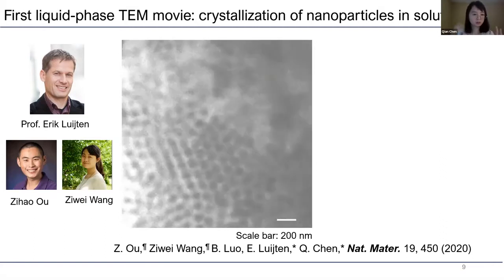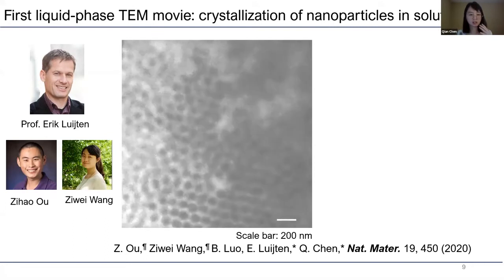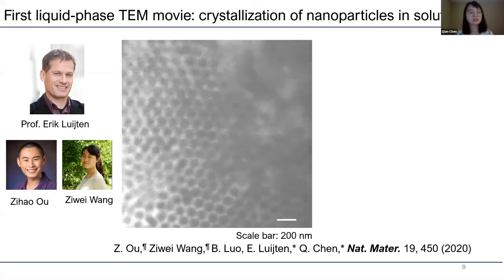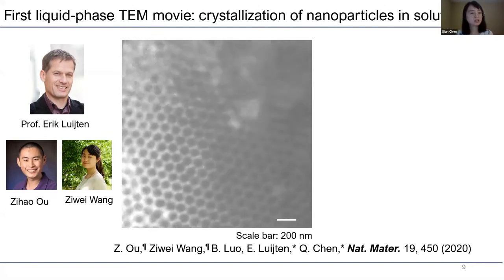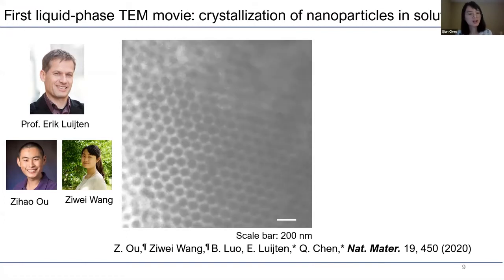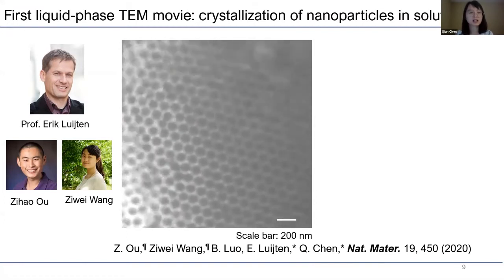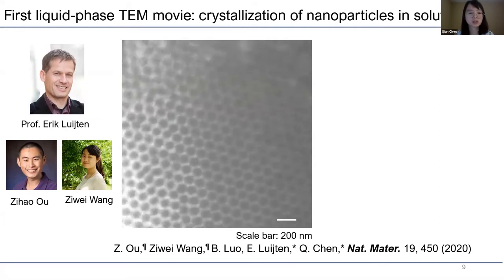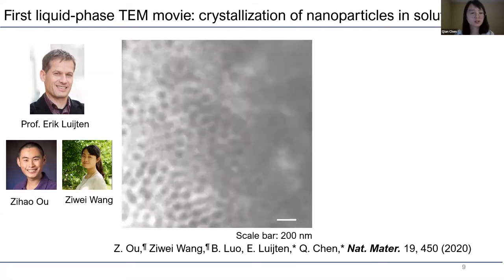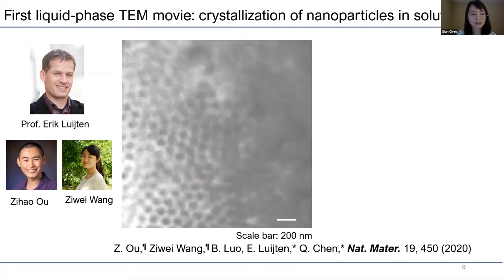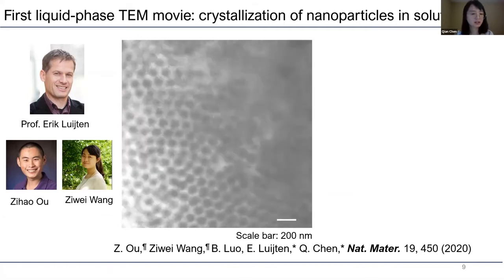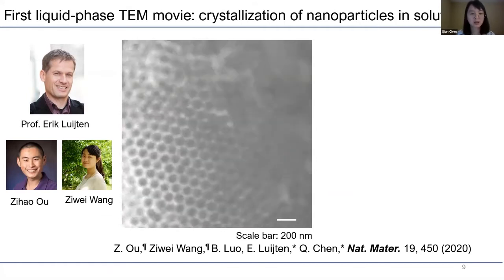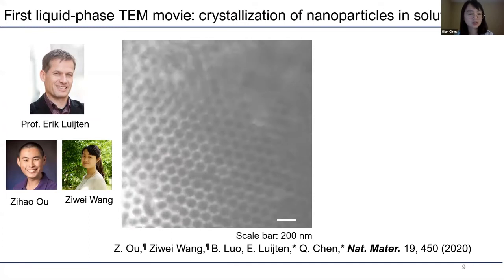At the very beginning, the movie looks very cloudy. You see dark shapes flying in and out, and that's because nanoparticles are undergoing Brownian motion in solution. But gradually, you can see a beautiful hexagonal lattice emerge from the disordered structure. That was extremely exciting for us because it was the first time we could see nanoparticle superlattice formation in real space and real time.